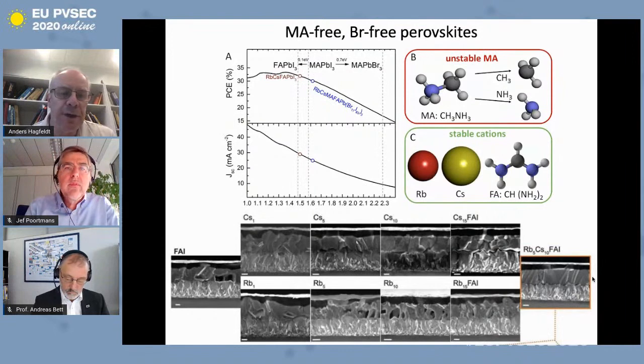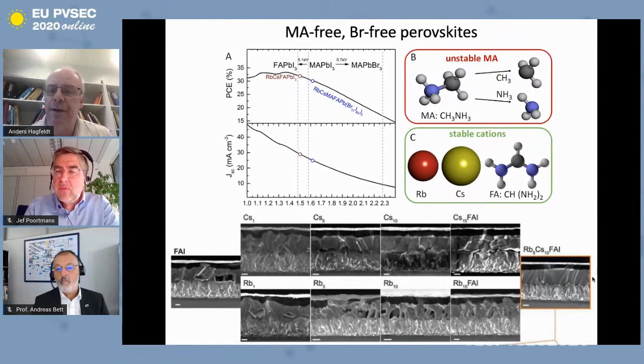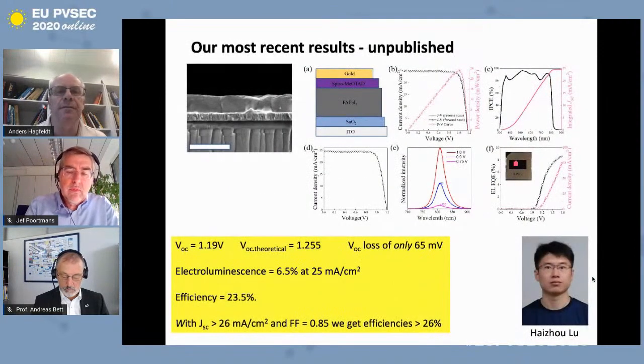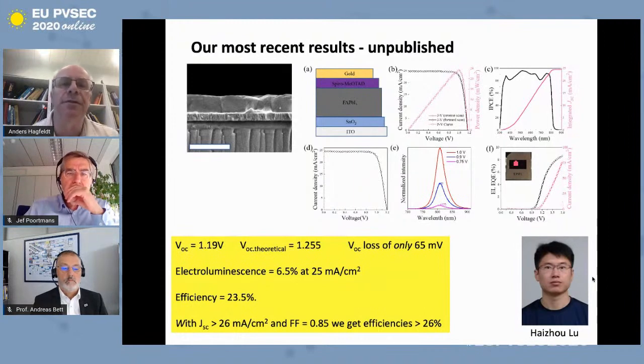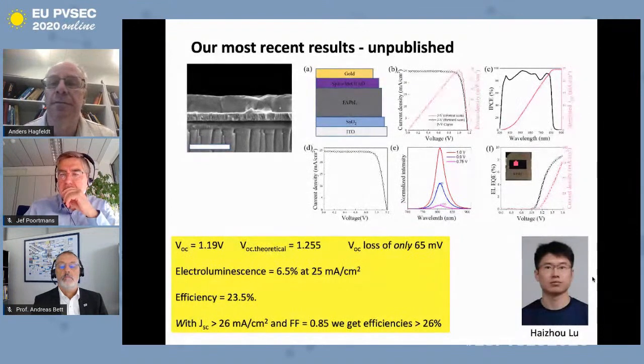If we follow the rubidium, you see that it's not very much a nice morphology. The efficiency is also poor. And our ideal composition became 5% rubidium, 10% cesium, and then 85% formamidinium. And that shows us that we can, with the compositional engineering, go towards formamidinium, avoiding methylammonium and bromide at the same time. So just to give you where we are at the moment, this is work accepted in Science, will be published in about a month, where we are really very close, or even I would say pure FA lead I3 due to compositional engineering and treatments in the process.